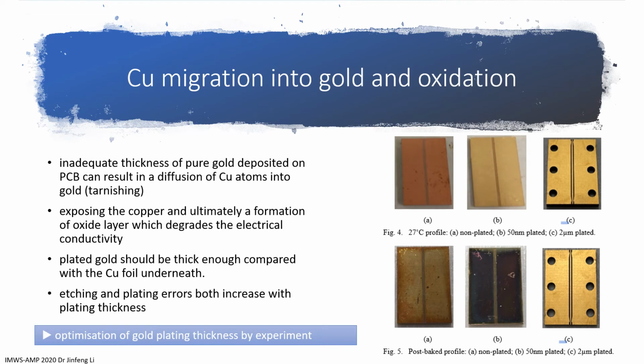This is evidenced by the insertion loss measurement shown later for the assembled phase shifter with different gold plating thickness, but with the same delay line length for the pi shifting at 60 GHz. Out of the concern of the copper migration and the malfunctioning, the plated gold should be thick enough compared with the copper foil underneath. However, the etching and the plating errors both increase dramatically with the plating thickness, resulting in a substantial deviation from the ideal right-angle design of the conductor profile. Optimization of the gold plate thickness in this study is arguably a compromise between the theoretical insertion loss and the practical limitation from the liquid crystal-based device manufacturing process.